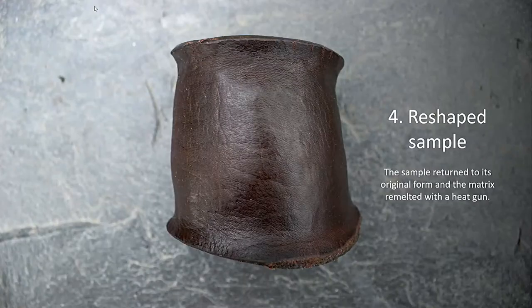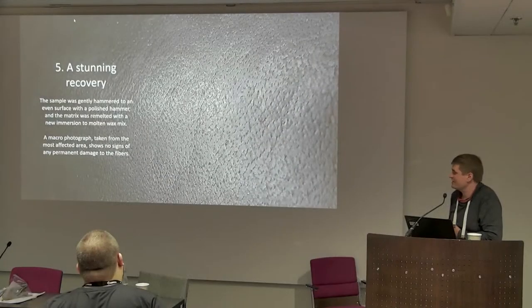Here it's reshaped back to its original form, by reshaping it and heating with a heat gun or hair dryer in this case. And finally, I wanted to see if any fibers were actually damaged. So I hammered it with a polished hammer to an even surface, and then did another round of wax immersion. This is a macro picture from the area that was most affected by the hammering. I could not find any damaged fibers in this picture. I think it's a really cool example of how you can recover wax hardened leather and why it's practically indestructible.